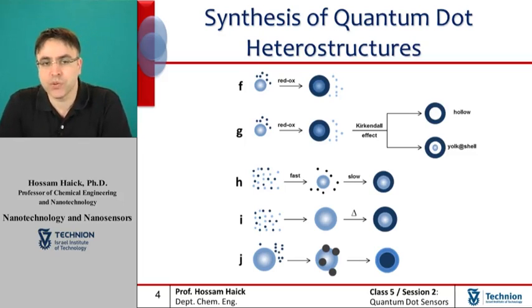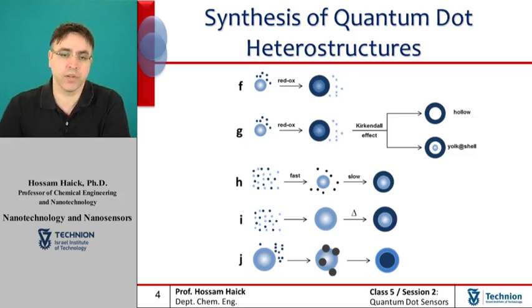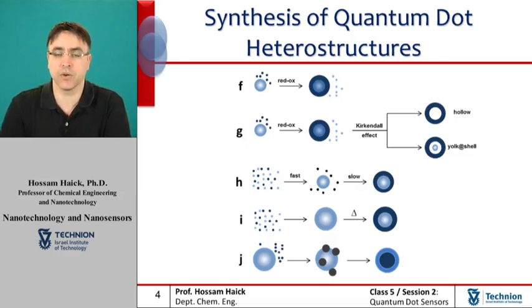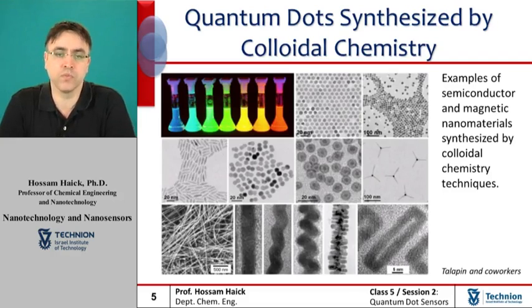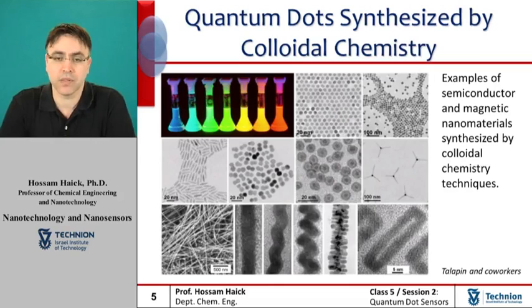Panel H shows a self-controlled nucleation growth in which all necessary ingredients for material formation are simultaneously present in the same growing solution. The experimental procedure is simplified since no separate seed preparation is required. Panel I shows thermally driven crystal phase segregation, and Panel J shows solid-state diffusion and coalescence. Starting with the preparation of simple objects like spherical nanoparticles, the field is now moving towards more sophisticated structures where the composition, size, shape, and connectivity of multiple parts of a multi-component structure can be tailored in an independent and predictable manner.